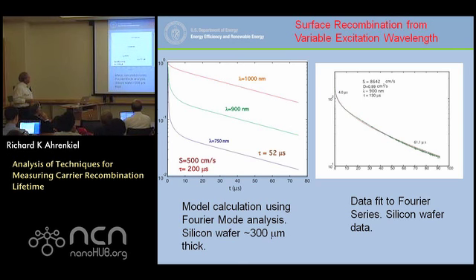Let me see here, what did I put in? Oh, okay, here, we assumed an S of 500 centimeters per second and a bulk lifetime of 200 microseconds. But what we did change here was the wavelength. Now we can do this with a tunable laser system. And here's what happens. If we put in a strongly absorbed, like this was 750 nanometer light, and the absorption's in a few microns. The carriers are generated near the surface in a Beer's law profile.